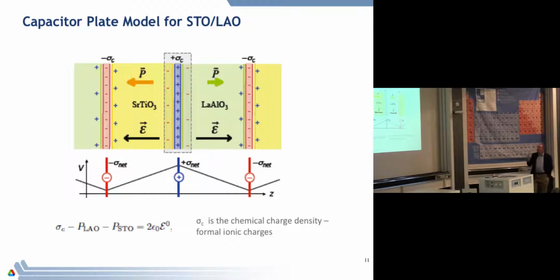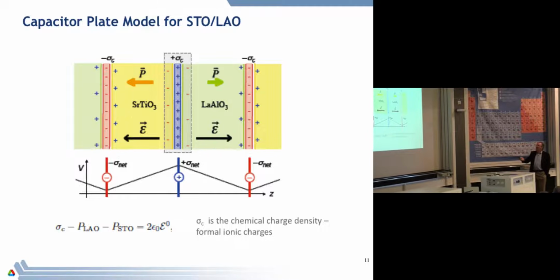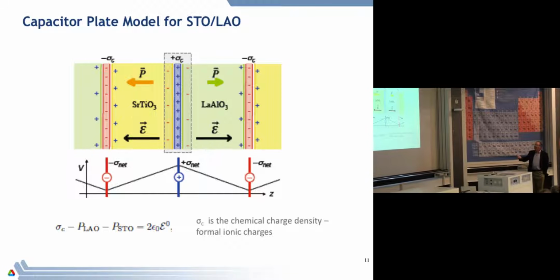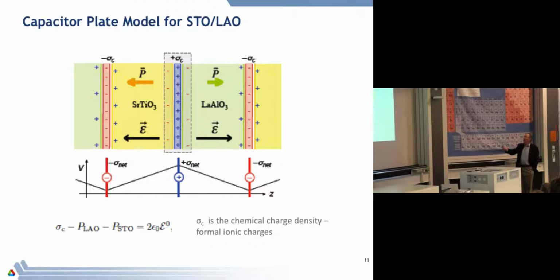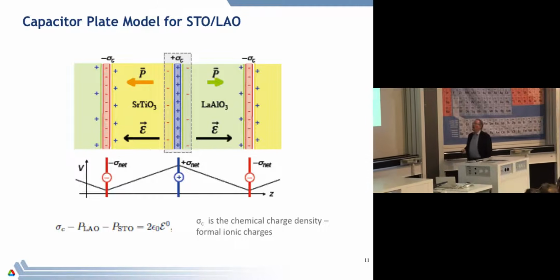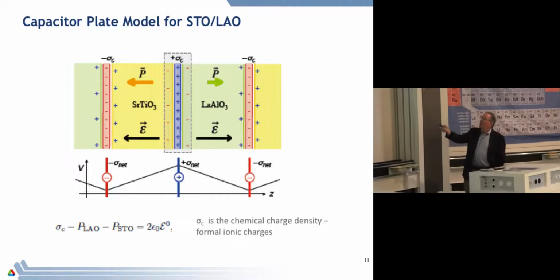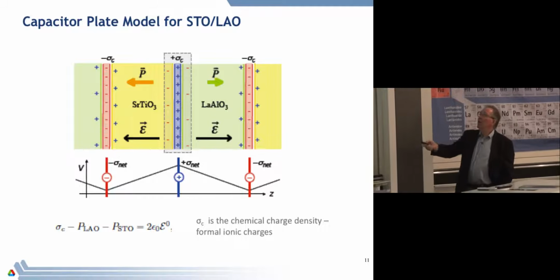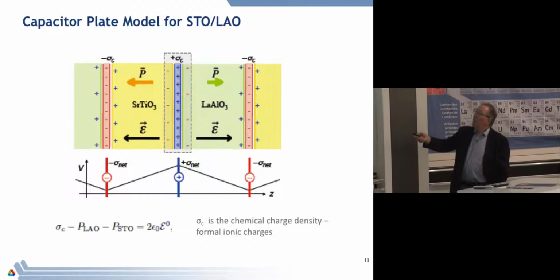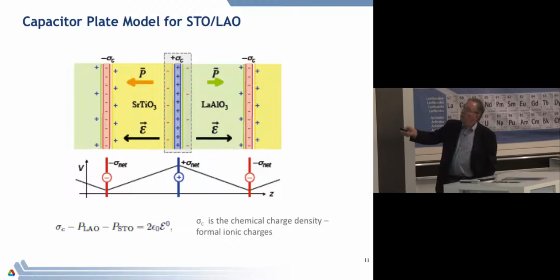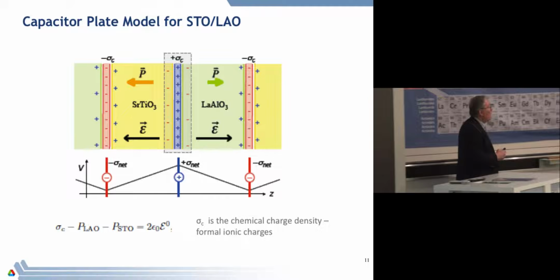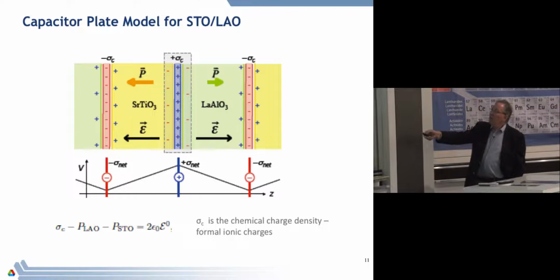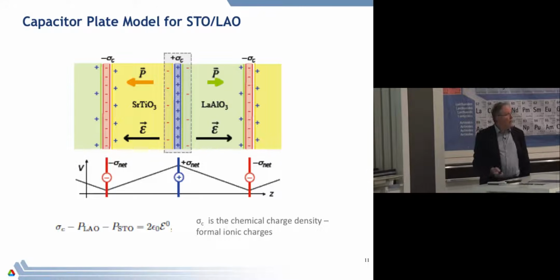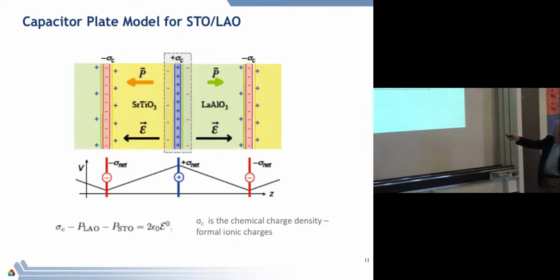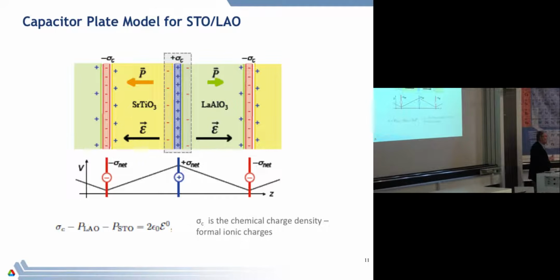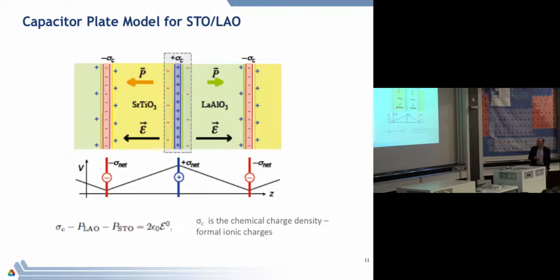So let's imagine making this material, and let's make a heterostructure, a repeating heterostructure of this strontium titanate, lanthanum aluminate, strontium titanate, lanthanum aluminate. And depending on how I end the interface, it can be with a positive or with a negative. And so that means that there will be an electric field now which is pointing like a capacitor plate from one to another, this way. That means that if I look at the potential, which of course is the integral of the electric field, there's a potential which will zigzag up and down like this in this pristine structure. And you know, that is indeed correct.